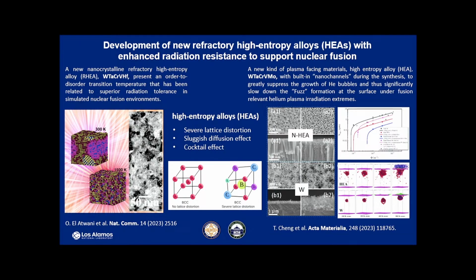And in recent years, high entropy alloys have got a lot of attention, especially refractory high entropy alloys. People were trying to find tungsten-based alloys to deal with the issues which pure tungsten has. And this is work we did at Los Alamos, through PVD again. You can do a many-element system there. It's a single phase BCC system, and then you can change the transition temperature from order to disorder. In the end, you increase the radiation tolerance of this material.